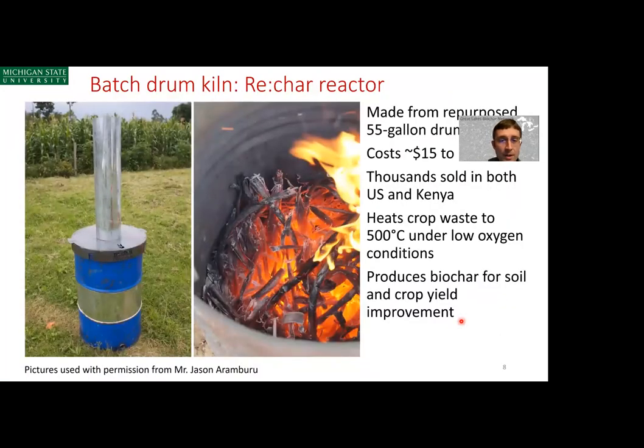You can also perform slow pyrolysis in a batch drum kiln—this is just a 55-gallon barrel. This system costs about $15 to make, and this company, Re:char, has made thousands of these and sold them in the US and Kenya. You can get temperatures around 500 degrees C under low oxygen conditions and make biochar, in this case, for use as a soil amendment to improve crop yield.